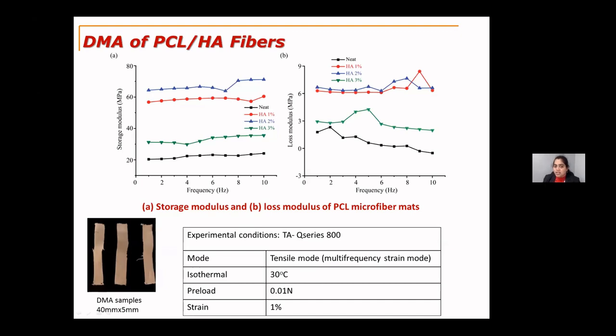method. And we have to note that the melting point of the PCL is between 55 to 60 degrees. So I did not vary the temperature here. I did not do the DMA based on temperature variation. I chose to do the DMA based on frequency variation, where I changed the frequency from 1 to 10 hertz, and then I did a multi-frequency strain mode with a frequency sweep method for the DMA.